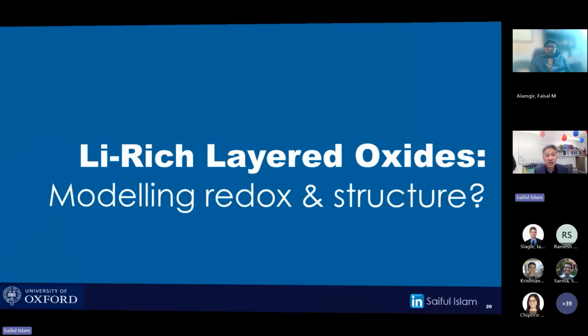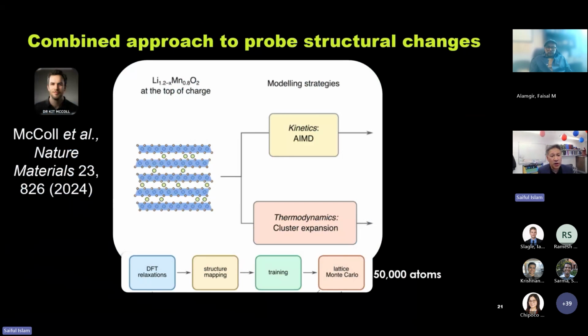So what do we do? In my group, led by a superb postdoc, Dr. Kit McColl, we've used two approaches. What I'm showing you is a schematic of our approach. At the top of charge, we use two modeling strategies. To look at the kinetics, we use standard ab initio molecular dynamics, but for longer timescales. But to look at the nanostructural and large-scale structural changes and the thermodynamics of these changes, we use a cluster expansion approach, which uses a large number of DFT relaxations, more than 600. We do some structure mapping, we do some training, and then finally some lattice Monte Carlo of more than 50,000 atoms. And DFT can only look at typically 200 to 500 atoms, so this is orders of magnitude larger.